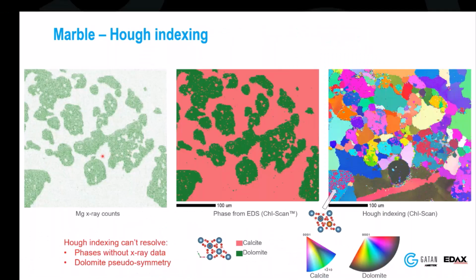We actually look at a data set here. We can tell the dolomite from the calcite pretty straightforwardly by looking at the magnesium map. And of course, if I do phase analysis on this using EDS data with chi-scan, we can see we do a pretty good job of pulling this apart.